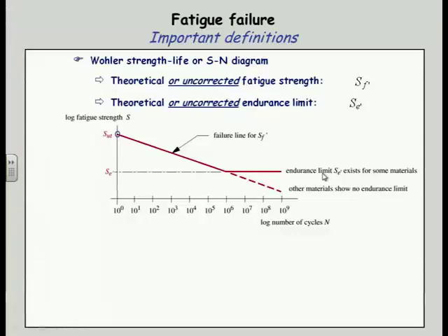much like the tensile test, on a specimen of a particular size and shape. It's usually round, looks a bit like the tensile test specimen. It's a little bit different, this one's a standardized size. It's about that long. You can hold it in your hand. It's about 10 millimeters in diameter at the belly, actually more like maybe 8 or 9. It's 3/10 of an inch in diameter at the smallest diameter. And there's some detail on the end so you can grab it.